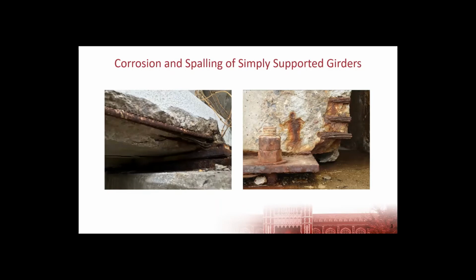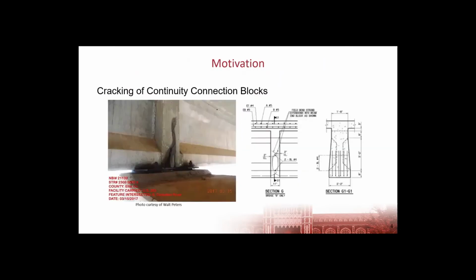So there are a lot of ways that we could eliminate these problems. One of them is to reduce the number of deck joints to begin with. And in a number of bridges in Oklahoma, this was done by creating continuous spans between our precast members with individual continuity connection blocks. So the ends of the girders would be connected using extended pre-stressing strands from the end of each girder, some mild steel rebar in some cases, and then a concrete block cast to connect the ends of those two girders, which would make them continuous for live load.